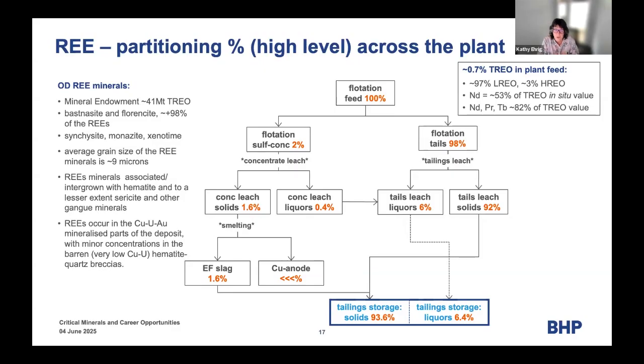So in the smelting side, because we don't smelt 100% sulfides, we actually have a little bit of gangue minerals in our concentrate. And during that smelting process, the copper that's generated, in the blister anode, really contains no rare earth elements in it. But the electric furnace slag, which is one of the exit streams, besides sulfur going into our acid plant, where the iron and the silicates are left, the rare earths actually end up in that slag.